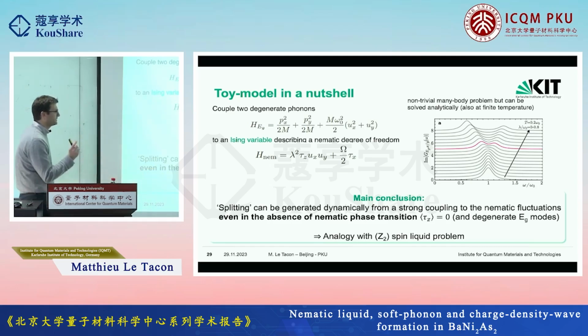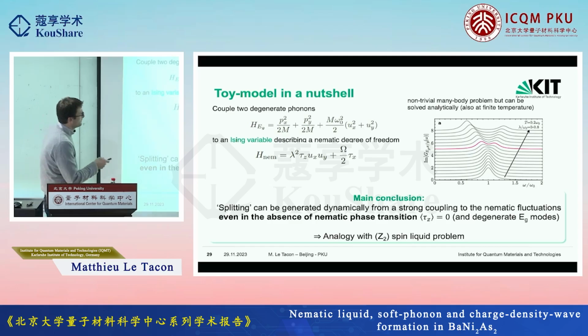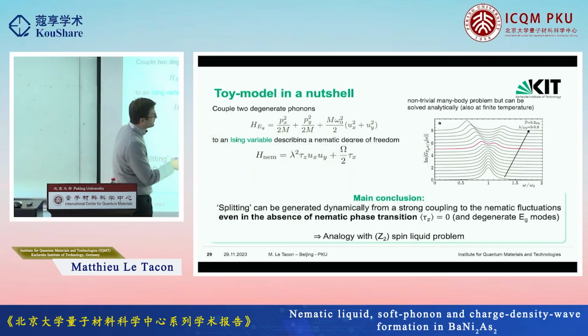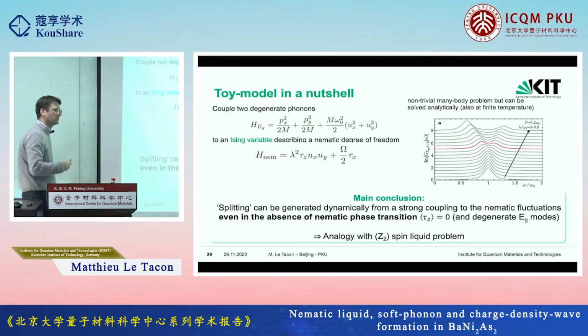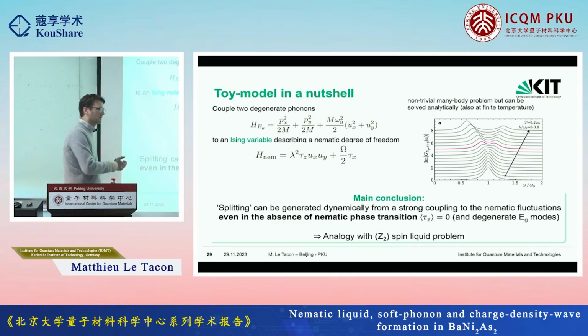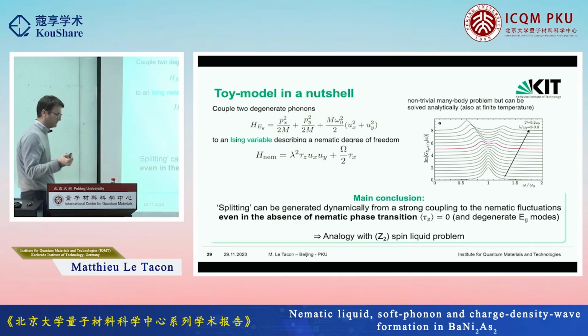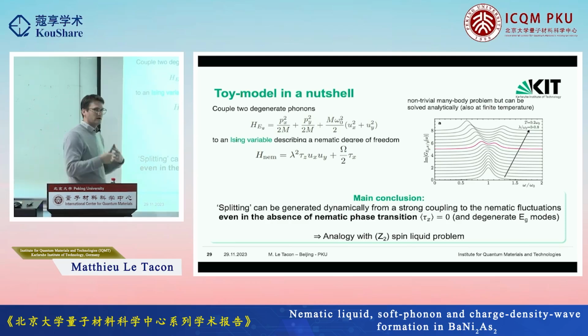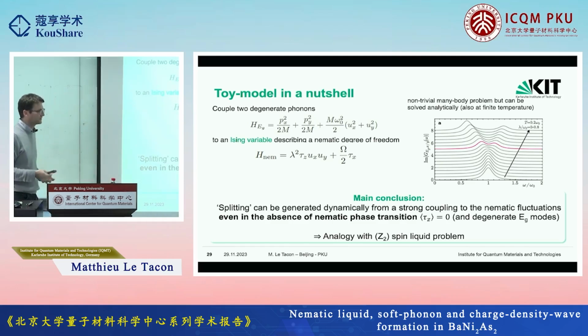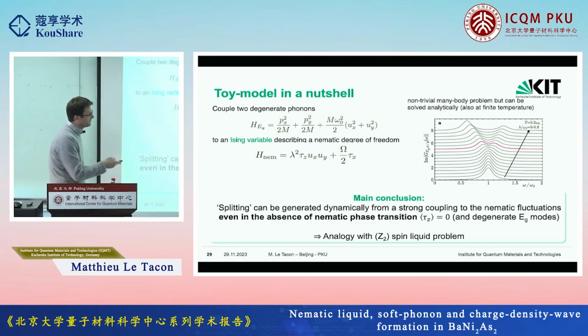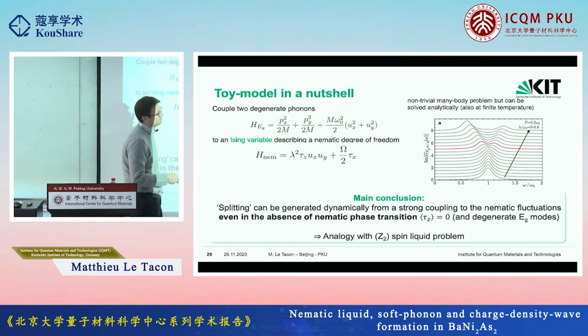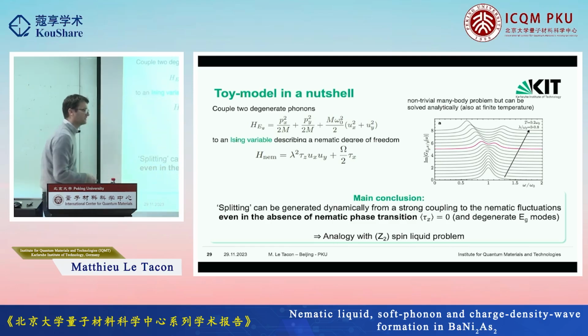But there is a whole nice regime where the coupling is large enough but small compared to the typical frequency of the phonon, where essentially from the phonon point of view, it's just as if the system had this degeneracy lifted. So you can think of the phonon as a finite frequency probe of the dynamics of the system. And your phonon at low frequency basically sees that the mode splits like that. That's also why if you go to a higher frequency phonon, the splitting that you see, or the change of the line shape, gets smaller.